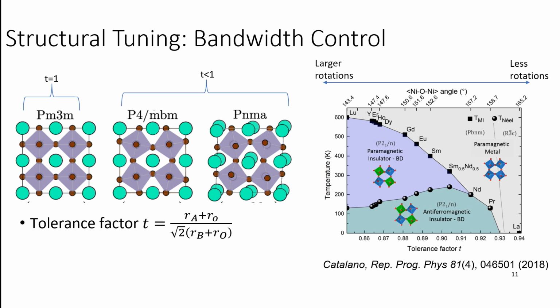The other way you can change the properties, just a really quick review again, is that you can also change the size of the rare earth ions that sit at these sites here. If you have a very large ion sitting at this corner in this structure, where these green balls are located, those octahedra do not rotate. So you end up with this nice, perfect cubic structure. And as you progressively reduce the size of these ions at these locations, these octahedra tend to rotate to fill up the volume of space.